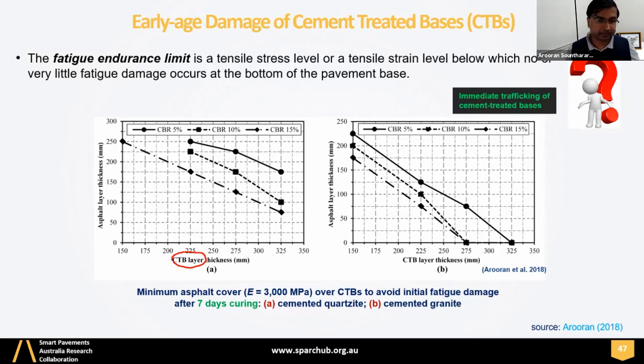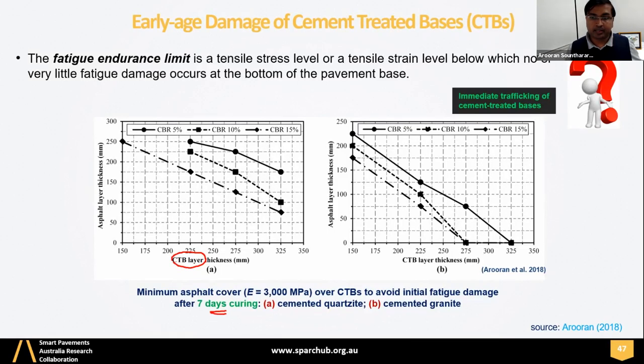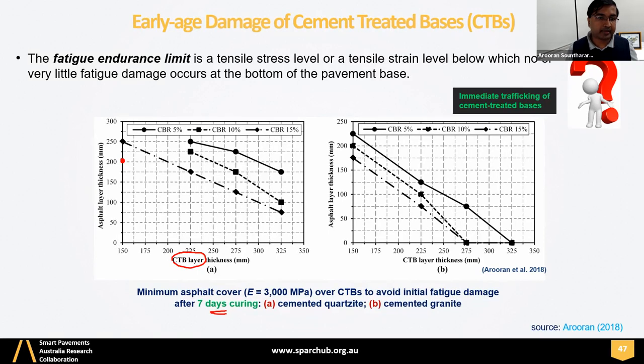If the minimum layer thickness is achieved within the specification, right? If I take an example, say this is 7 days curing, I wanted to check the minimum CTB layer thickness for my asphalt layer thickness 200, right? So I'm constructing 200 millimeter asphalt layer thickness for a given traffic. And then my subgrade CBR for this instance, I would take is 15.